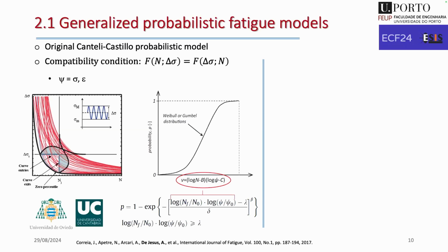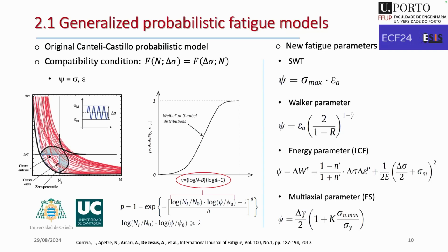That was possible with the discovery of this function, the V function, which combines the number of cycles and the fatigue parameter. This approach is well known nowadays, but in the original idea of the authors it was explored just for the stress or the strain parameters, as we used to see in our S-N fields. Then, with our collaboration, we started to realize, okay, this is much more powerful than the original authors found.